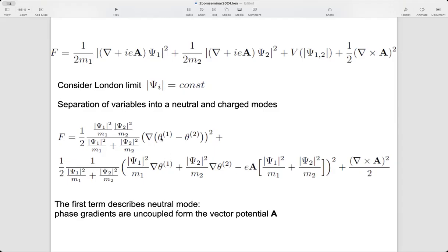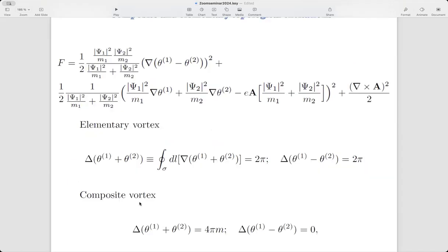And if one has a composite vortex where both phases wind by 2 pi, this term is cancelled, it is 0. And as we'll see below, that means that an elementary vortex in this system has logarithmically divergent energy, while a bound state of two vortices has a finite energy. It has very important consequences for the phase diagram of the system.